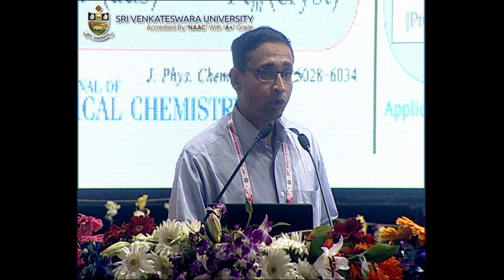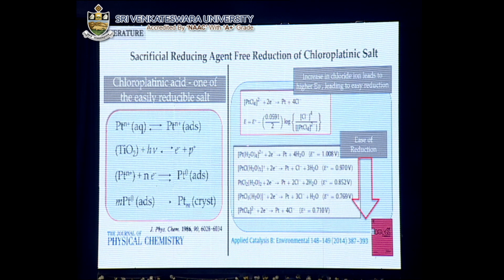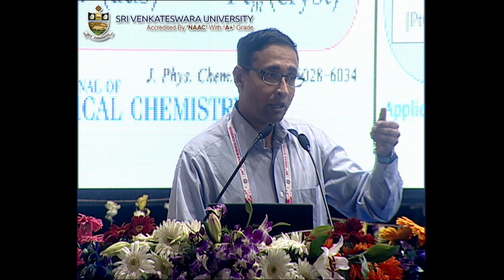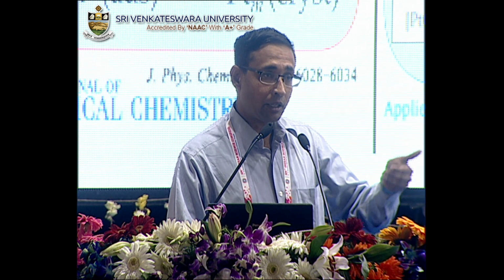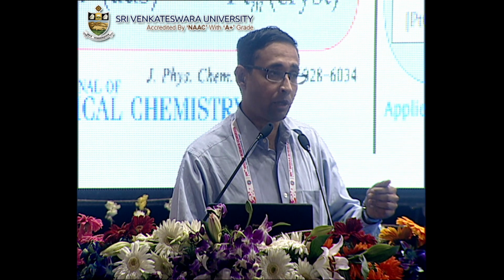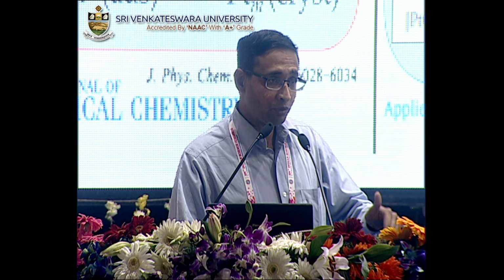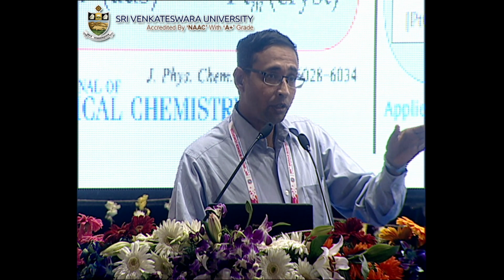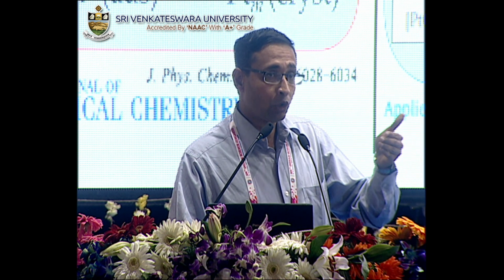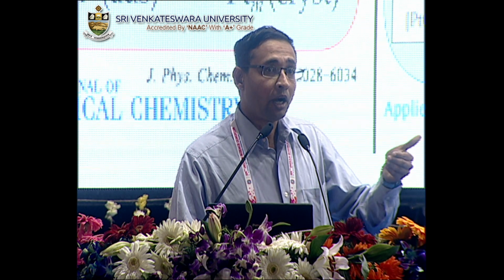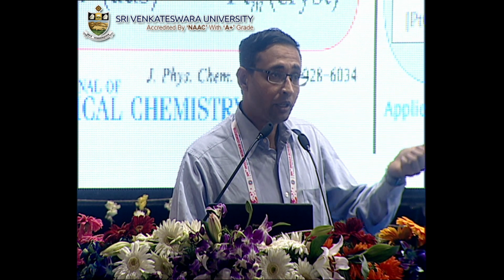When we use a photocatalyst like TiO2, the TiO2 is a material which gets excited in the presence of UV light. The electrons in the valence band, that is, the non-active electrons, can get excited in the presence of UV light, and this makes the electron available for some other job. When the electron jumps from the valence band to the conduction band, it reduces the chloroplatinic acid, which is the platinum precursor, and this platinum gets studded over the TiO2 itself.